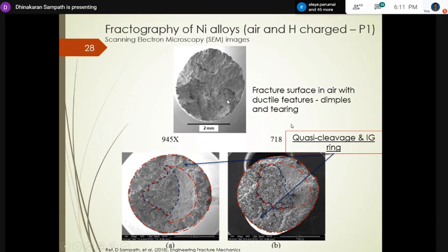945X, see, in this case the reduction of area is huge, but here it is very, very minimal. There was no change in the cross section due to necking. Here also, we can see flat facets originating from cleavage or twin boundary cracking.